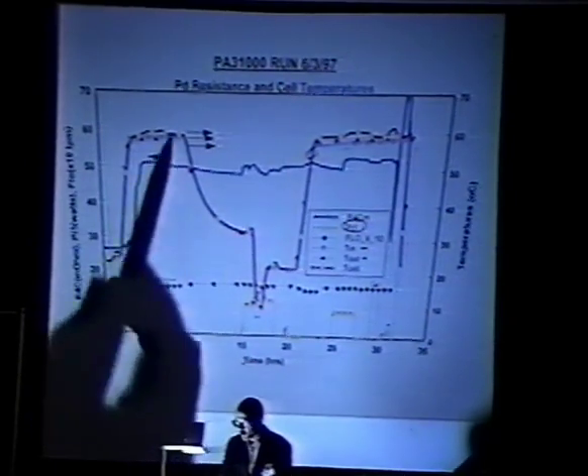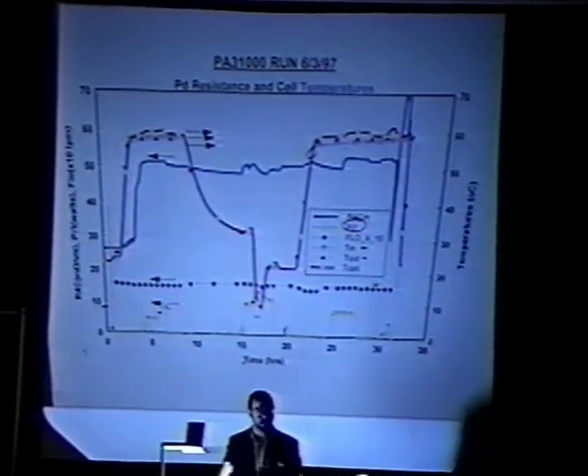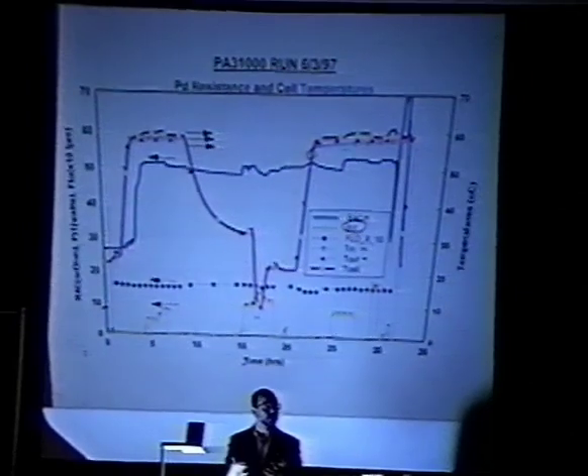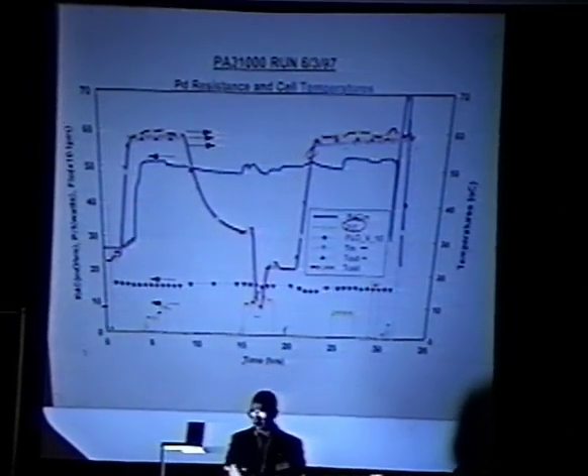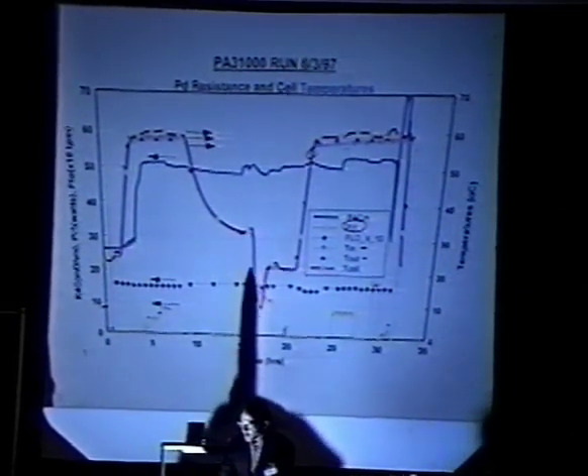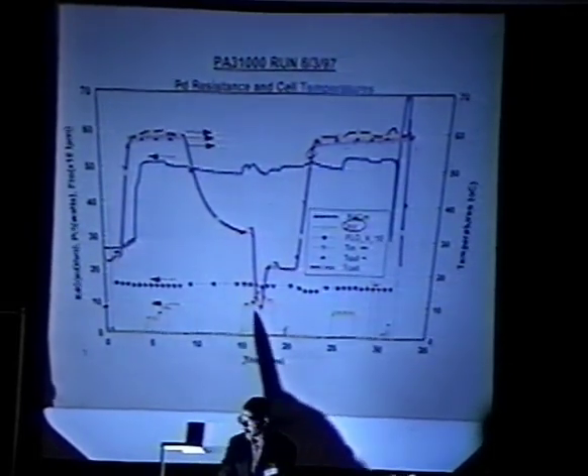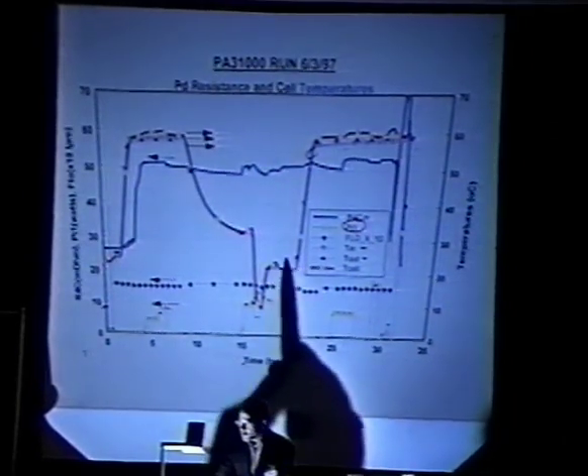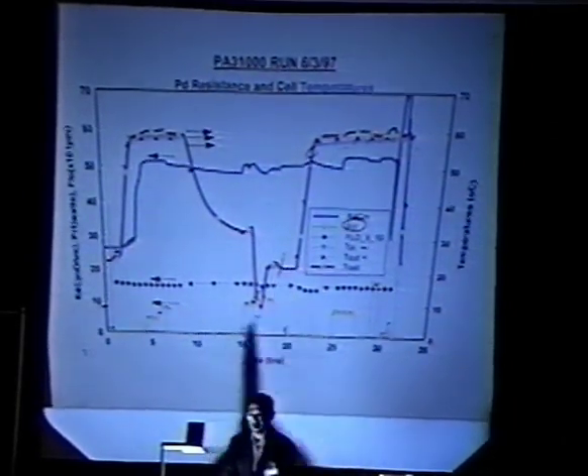On this particular run, did nothing, it made no heat, there was no evidence of any type of heat, no activity in the cell. Basically, it was very clean and clear, except when I turned the electrolysis current on. And then after cooling, real fast cooling, down to 10 degrees centigrade, then I forced it back up to room temperature and just let it sit. And it's somewhere right in here where the power takes off.